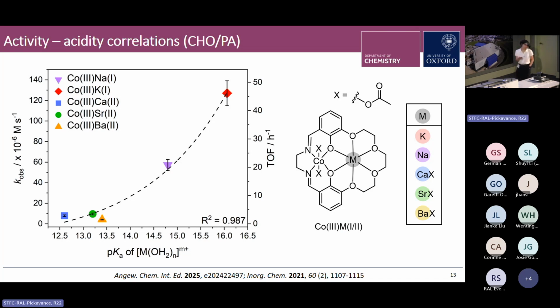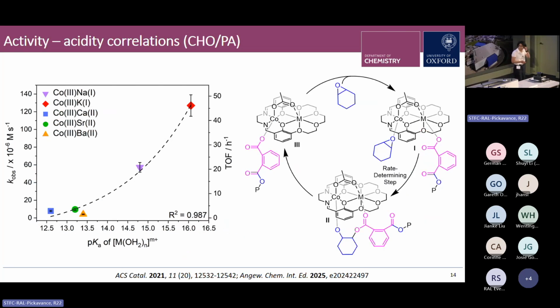And we can rationalize this correlation with respect to the proposed catalytic mechanism, which is supported by experimental and computational investigations on related systems. And what we can see, this involves the rate determining step where the epoxide is activated by cobalt, which is then ring opened by this S-block metal bound carboxylate nucleophile that forms an alkoxide intermediate, which can undergo rapid insertion of the anhydride to reform the carboxylate, which then shuttles back on to the second S-block metal. So we can rationalize the trend by considering the rate determining step, and in particular, this key rate determining